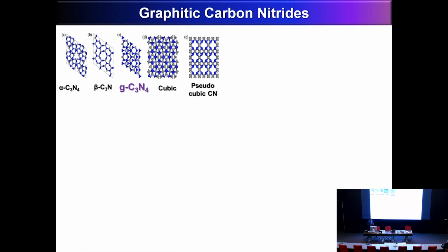The material I'm going to talk about is graphitic carbon nitride, which is a fascinating material. It's composed of carbon and nitrogen. There are 5 different kinds of carbon nitride: alpha, beta, cubic, pseudo-cubic, and graphitic carbon nitride. Among these, graphitic carbon nitride can be synthesized from chemical or molecular precursors at low temperature and low pressure. But alpha, beta, cubic, and pseudo-cubic carbon nitride, which are quite stable materials, need extremely high temperature and pressure. And also you can't make them in large quantity. So therefore, many people have been working on graphitic carbon nitride.